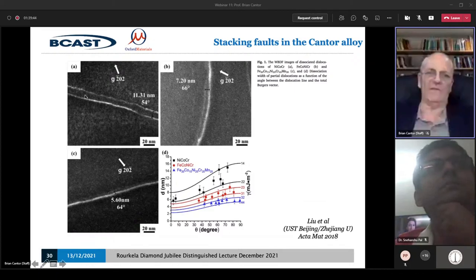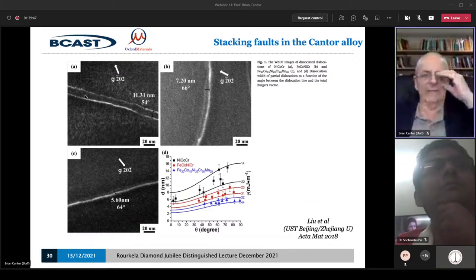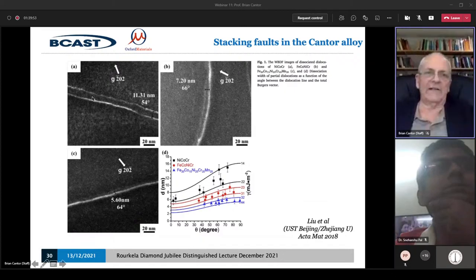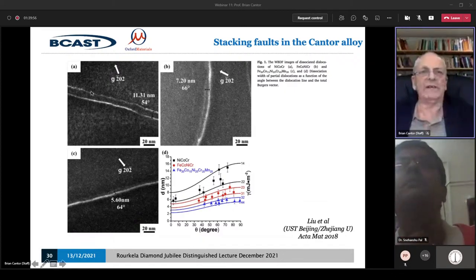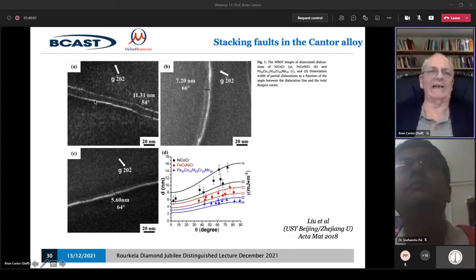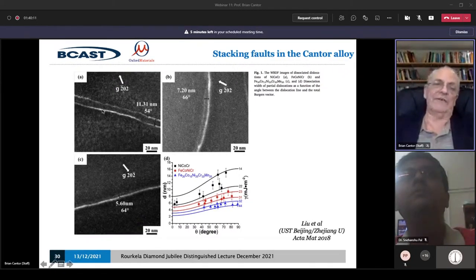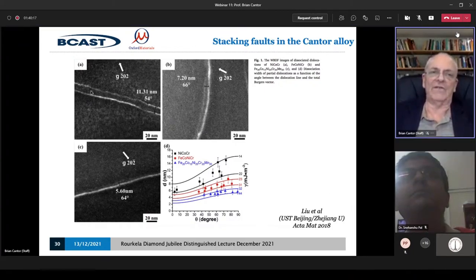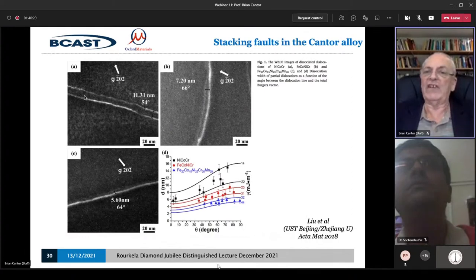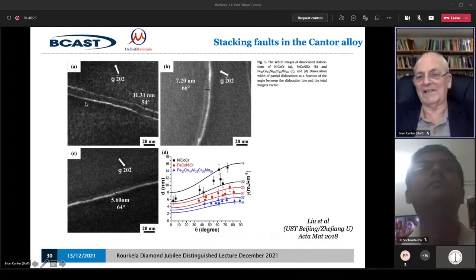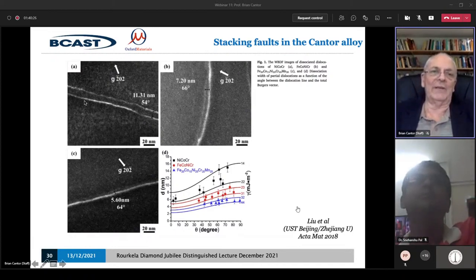Now, in materials with high stacking fault energy, like aluminium, the separation is very small, and that affects the characteristics of the dislocation flow in the material, and therefore the fracture resistance. In materials with a very low stacking fault energy, a good example being stainless steel, the separation gets much bigger, and that gives different characteristics of how the deformation and the formability take place. So the formability of stainless steel and aluminium are very different because of the stacking fault. I'm saying this because other people may not know.